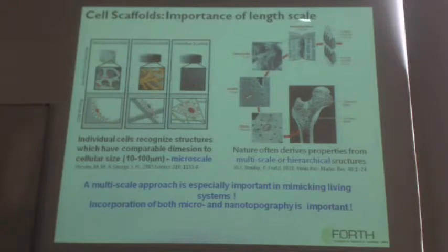Here you can see, for example, the structure of the bone. You can see that it comprises multiple length scales starting from collagen molecules at the nanometer scale, fiber bundles at the micrometer and lamellas, and finally at the macro scale, osteons, and this is actually the bone. So a multi-scale approach is especially important in mimicking living systems. So incorporation of both micro and nano topography is important to realize in cell scaffold materials.